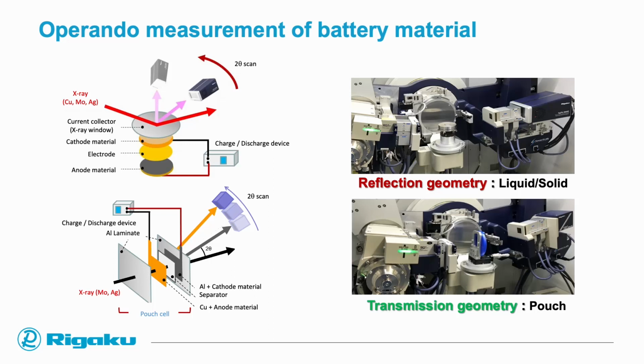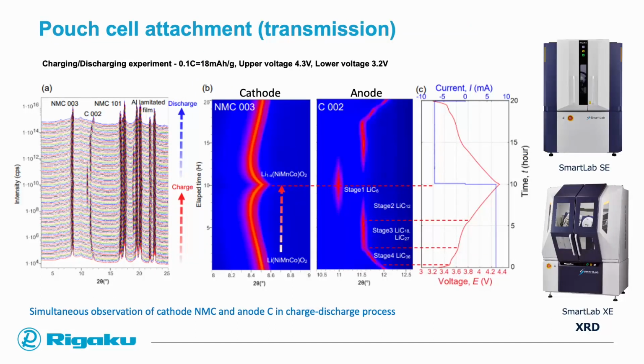Together with the sample stage, it is also necessary, of course, to provide a potentiostat, so a device which guarantees the charging and the discharging of the cell and monitors the voltage and current curves. Once this is set, also with the choosing of the proper source, for that case, Rigaku offers, besides the common copper source, also molybdenum source, which is much more suitable for analyzing thick cells and also these reflection geometry cells because of the shorter wavelength. Once this is set, the charge-discharging experiment can start.